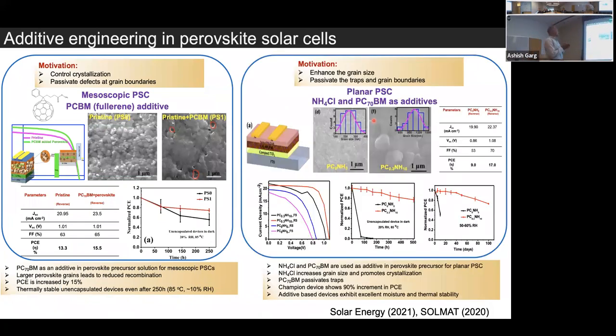Finally, this is the last slide. We have also done additive engineering by adding additives to perovskite. In this work, we have added PCBM, which is a C60 molecule, into the perovskite layer. Generally, people believe that PCBM doesn't work as an additive, but here we have purposefully used it as an additive, and we found that using PCBM improves the stability of the device by about 20% or so. The reason is, one, it leads to larger grain size in the perovskite film, which reduces the recombination, and we increase the efficiency by about 15% and get better stability, effectively reducing the trap density in the material. Second, we use the additive to increase the grain size.